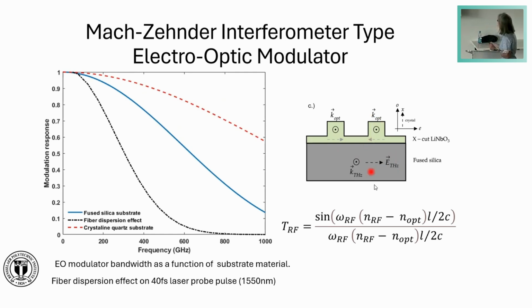Since the silica is much thicker than the thin film lithium niobate, the terahertz wave travels in the substrate. So what matters for the index of refraction for the terahertz wave is actually the index of refraction in fused silica, which is 1.95. For the optical wave, what matters is the material and also the waveguide geometry. Through the dimensions of the waveguides, like the height of the waveguide, it is possible to engineer the index of refraction for the optical wave. Therefore it is possible to minimize the mismatch of the two indices of refraction, and as a result to increase the bandwidth of the device.